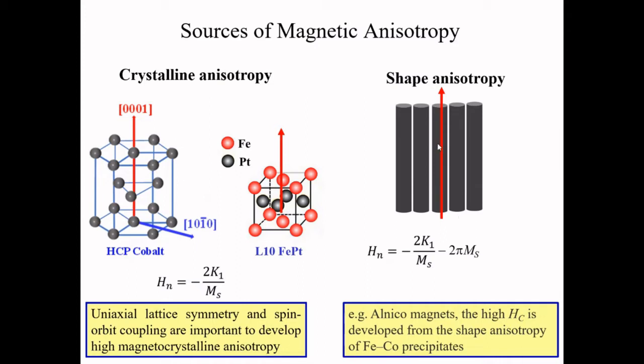Okay, but if we need to further introduce some outside source, shape anisotropy is one of the sources. If we design, let's say, a cobalt HCP cobalt nanorod shape, we can have both shape anisotropy and magnetocrystalline anisotropy together, and we can have a giant anisotropy. And then based on the giant anisotropy, we can develop high coercivity, which is required for permanent magnet design.